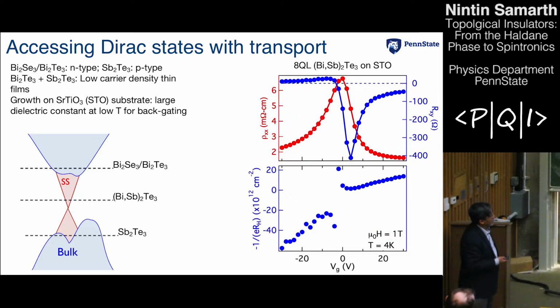And as we gate the sample, so this is the voltage that you apply, the red curve over here is the resistance of the sample, or the resistivity. And the blue curve is the Hall effect. And you can see that you take your resistivity through a maximum. This is where the Dirac point occurs. And at the same time, the Hall voltage changes sign because you go from electrons to holes. So despite the fact that these samples have these defects, you can grow samples in a form that allows you to change the chemical potential such that you're dominated by the surface transport, and you're not having a large conduction channel that is in the bulk.